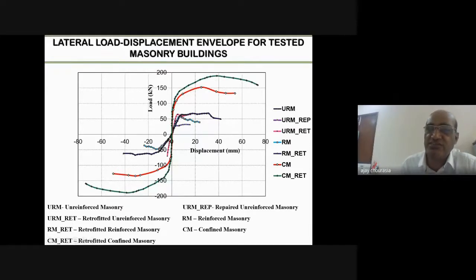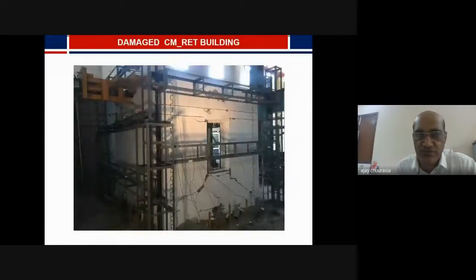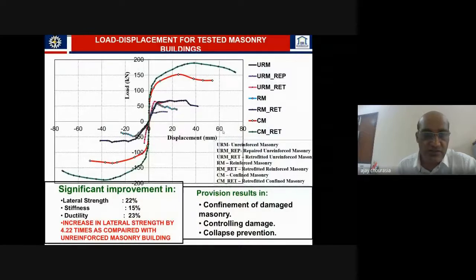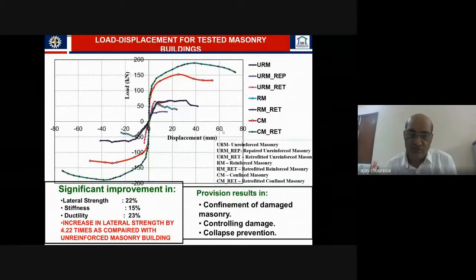Apart from that, there was a substantial increase in the energy dissipation capacity, that is the area under the curve of the hysteretic loop. That itself explains the significant improvement in the lateral strength capacity of the retrofitted confined masonry, which was 22%. In terms of stiffness and ductility, it was 15% and 23%. And the increase in lateral strength was 4.22 times when compared with the URM. So, having this kind of significant improvement in the engineering properties by provision of the retrofitting on the confinement.